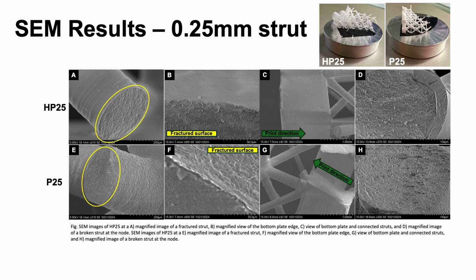A through D images were taken of the HP lattices, and E through H were taken of the P lattices. In A and E, we see a close-up of a fractured strut somewhat far from the node. We also see that the surface finish of HP is a lot smoother than that of the P lattice structure. When we compare B and F, we're looking at a close-up of a bottom plate. Again, the fractured surface and normal surface for P look almost identical.